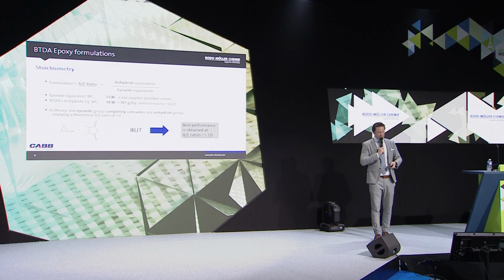Let's go a little bit into detail on how to work with this BTDA. First, we have to look at the stoichiometry, how a system using BTDA and epoxy resin should be formulated. What we would think is that we need a stoichiometry of anhydride to epoxy of 1:1, so one epoxy group can react with one anhydride group. But this is not perfectly true for those dianhydrides. What we saw in long R&D work is that it is much better to have a ratio of anhydride to epoxy which is far below 1 to get the best performance out of your thermoset system.